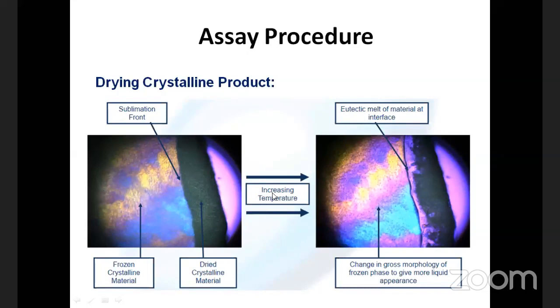Okay, so with increasing temperature, there is a change in gross morphology. You will see here the comparative this one and this one. So there is change or disturbances in the pattern of a dried material. This change in morphology of the frozen phase gives a more liquid appearance, and therefore the appearance is a bit shiny. So this is an indication that the eutectic temperature has been attained, and this is again considered as collapse temperature. So you can carry out drying below this temperature.